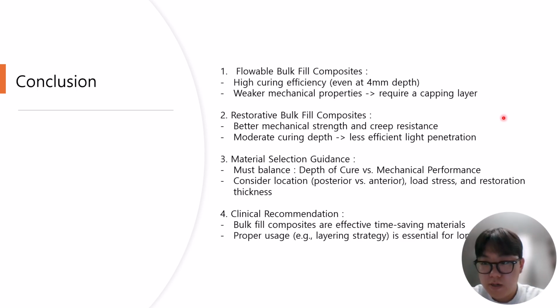To wrap up, here are the key takeaways from this study. First, flowable bulk-fill composites showed excellent curing efficiency, even at 4 mm thickness. However, they had weaker mechanical properties, so they must always be covered with a conventional composite layer, especially in posterior